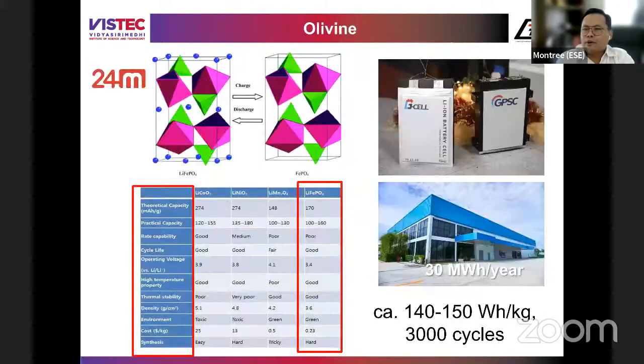So if you compare, for example, 30 megawatt hour per year of GPSC using 24M, their battery is going to be really expensive. They achieve 140 watt hour per kilogram. This is the LFP technology. The good thing is the cycle life. We have phosphate here. You can see phosphorus and oxygen here. Inside our body, we also have a lot of phosphate, buffer phosphate, right? It's really stable. It does not easily release oxygen gas, so it's really good in terms of safety. But we trade off here: high molecular weight, or too heavy.